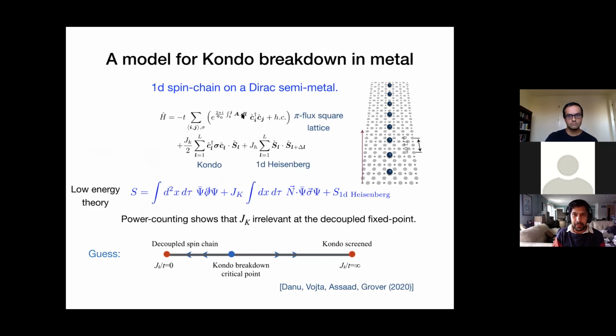We considered Dirac fermions, conduction electrons, Kondo coupled with a Heisenberg chain. This was already interesting. It has not been studied to our knowledge. And this doesn't have a sign problem again. That's interesting. The low energy theory becomes basically Dirac fermion Kondo coupled with some Néel order parameter, where the Néel order parameter is coming from this 1D Heisenberg chain. So this is some Wess-Zumino-Witten theory of the 1D Heisenberg chain.